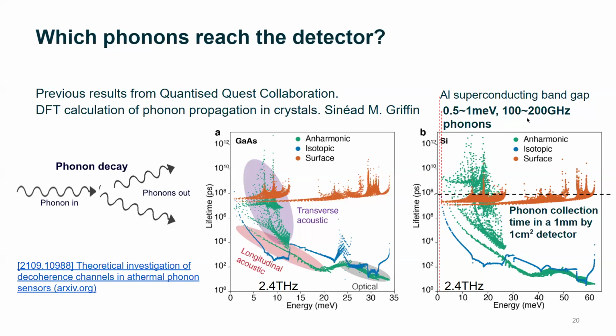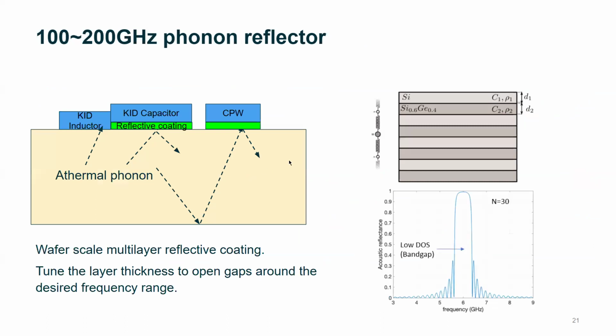So the answer is yes, we want to protect or preserve. For dark matter detection, we want to preserve the phonons in this energy range. And this is, of course, above the aluminum superconducting band gap. So what we can do is design a multi-layer structure that opens a gap in this frequency range and reflects phonons. We can put this coating everywhere below the superconductor other than this active superconductor region, which is the inductor. So the phonons will reflect off everything else, but only be collected by the inductor.